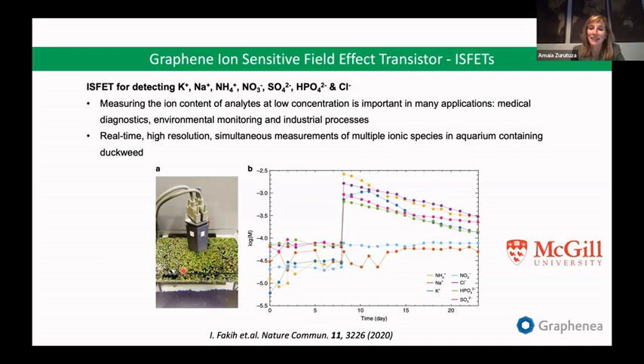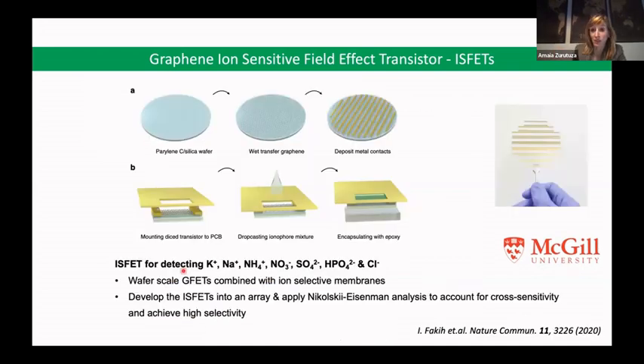Okay, so this work was done at wafer scale, at 4 inches, 100 millimeters. We transferred graphene onto parylene C coated silicon wafer, then deposited metal contacts, then split the individual devices. We put different ionophore mixtures that were selective for different ions, so potassium, sodium, and so on. And that's how we got a simultaneous measurement of the different ions.